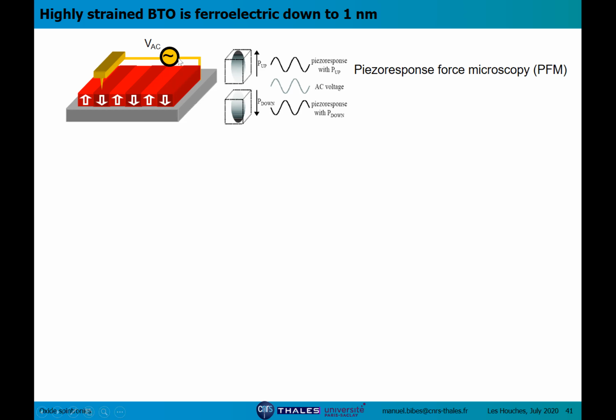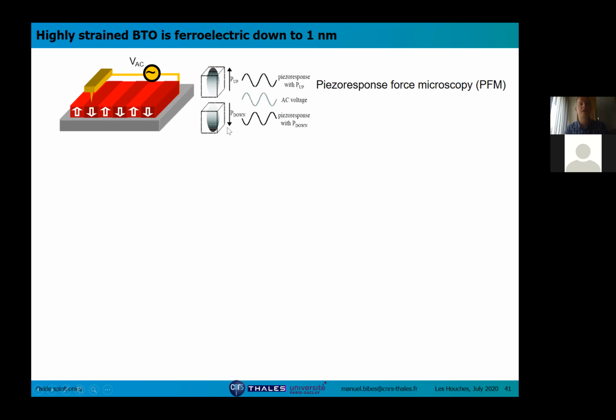is shown here. So basically, it's a contact mode AFM technique. And with the conductive AFM, we apply an AC voltage between the tip and the bottom electrode across the ferroelectric. And then we probe the ferroelectric through its piezoelectric response. So when AC voltage is applied, the ferroelectric will expand or contract due to piezoelectricity, and the response will be in phase or out of phase depending on the direction of the polarization, up or down. So if you scan a given area in the ferroelectric and you pick up the phase of the output signal, you are able to tell if the polarization is up or down.